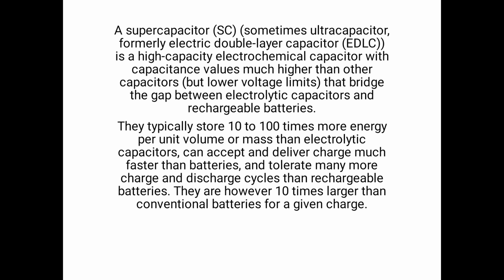A supercapacitor, SC, sometimes ultracapacitor, formerly electric double layer capacitor, EDLC, is a high capacity electrochemical capacitor with capacitance values much higher than other capacitors but lower voltage limits, that bridges the gap between electrolytic capacitors and rechargeable batteries. They typically store 10 to 100 times more energy per unit volume or mass than electrolytic capacitors, can accept and deliver charge much faster than batteries, and tolerate many more charge and discharge cycles than rechargeable batteries. They are, however, 10 times larger than conventional batteries for a given charge.